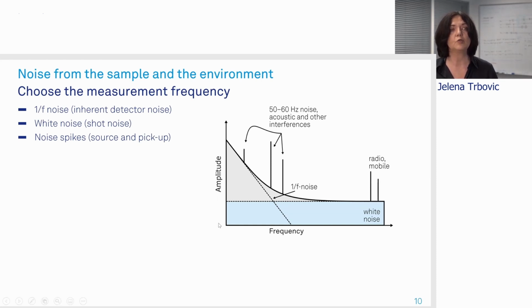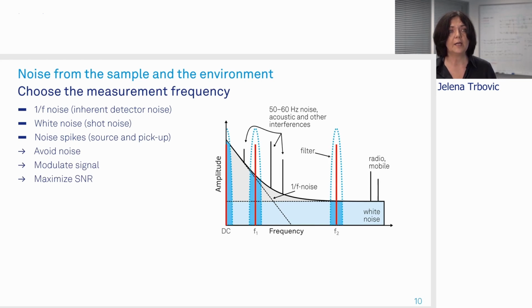And in that case, we need to look at the noise spectrum of the whole measurement system. And we will typically find the 1/f noise. We will also see the white noise. And what we want to do really is to try to be in the region where this noise is minimum. And of course, if we have spikes and pickups, we need to make sure we avoid those. And the way to do that is to actually modulate the probe for the measurement system and avoid these noise spikes and go into the region where we can get a higher signal to noise ratio.